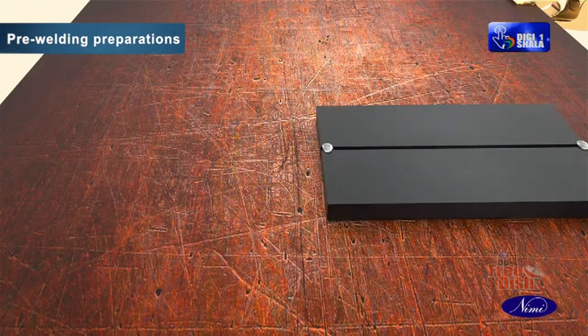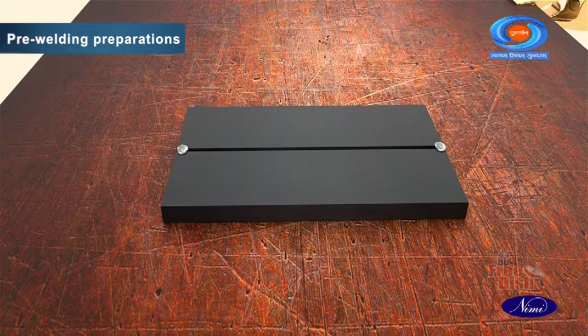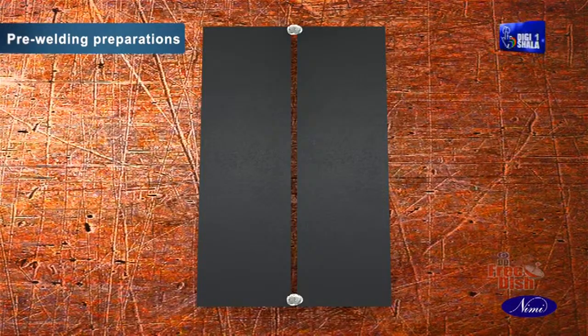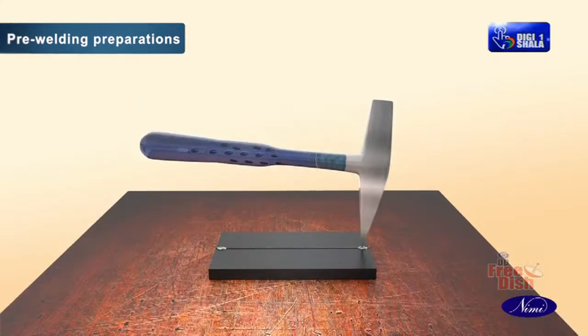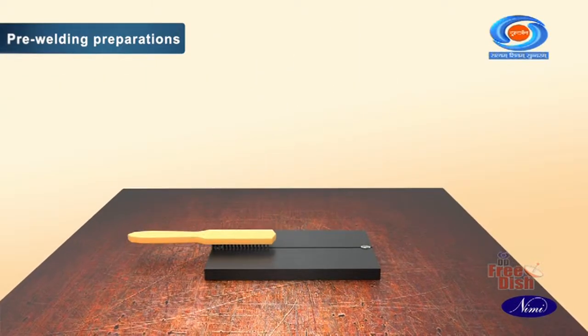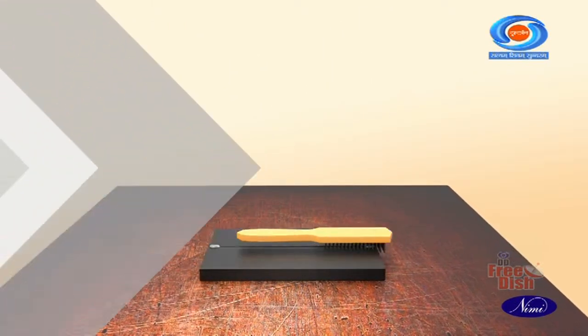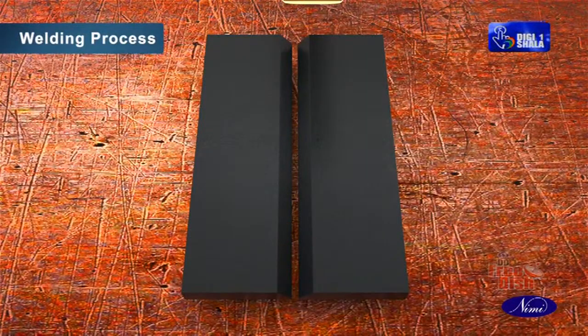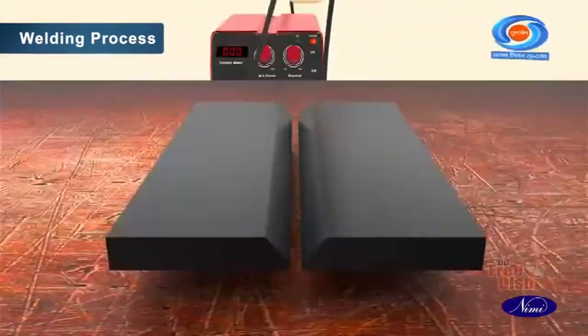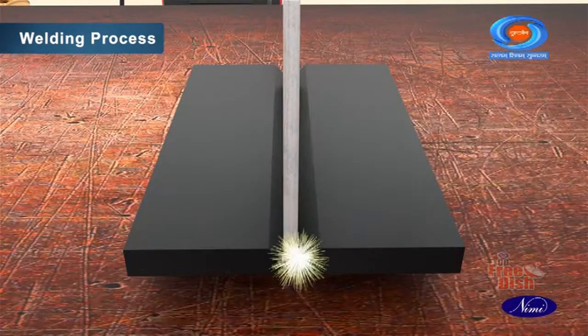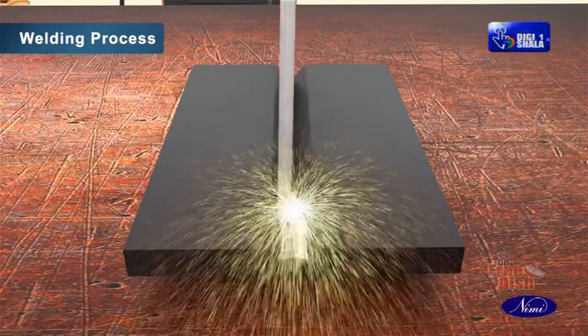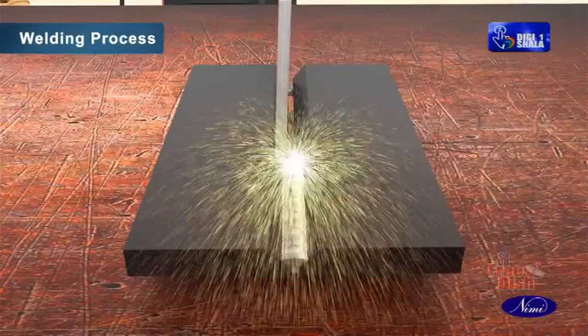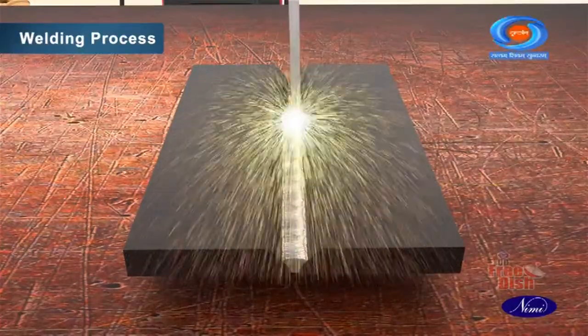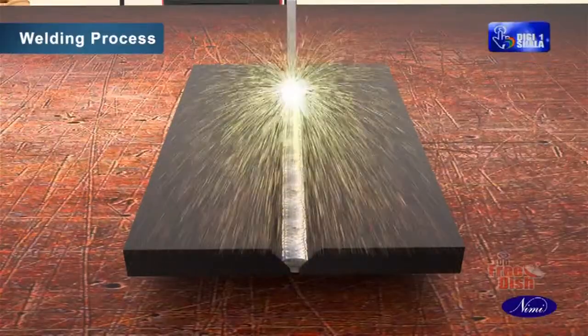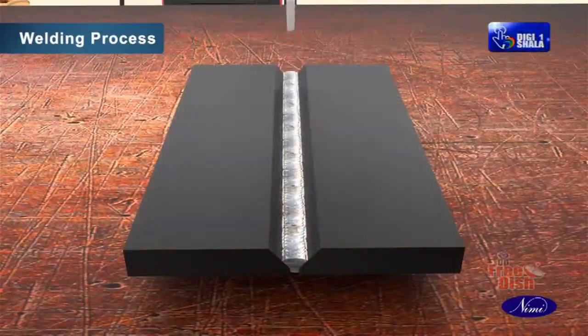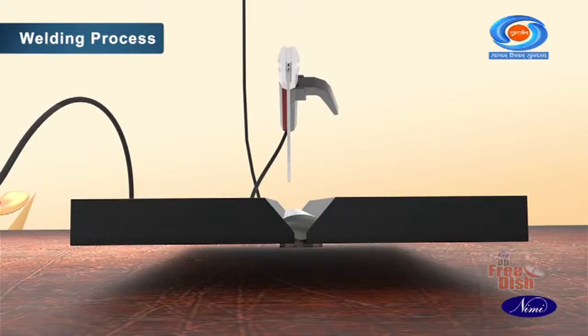Tack weld on the back side of the plates at the ends. The length of the tack should be 5 to 10 mm. Deslag the tack weld and clean. Position the tack welded job on the table in flat position, the single V portion facing up. Deposit the root run and fill the crater and take special care to maintain the keyhole, to ensure proper melting of root face and root penetration.